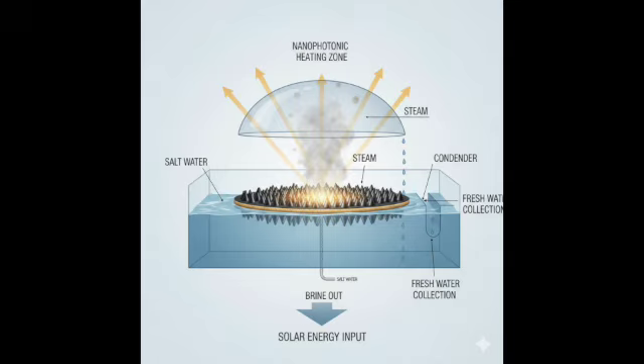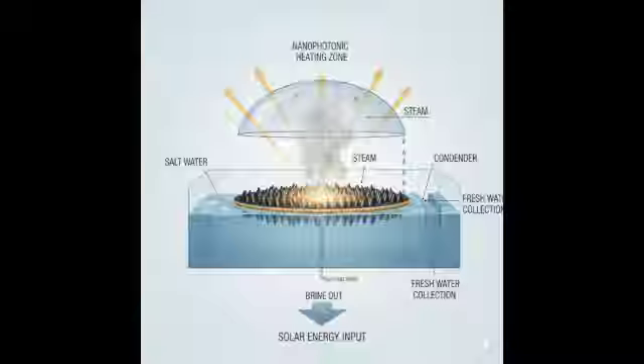Yes, it absorbs light well, but its real strength here is as an intermediate adhesive layer. You can coat a membrane with PDA and then easily attach other functional materials onto the PDA layer, things like carbon black nanoparticles for enhanced heating, or maybe a superhydrophobic molecule like FAS17 to improve wetting resistance. So it's a platform for building multifunctional surfaces. Exactly, and it's relatively simple, uses water-based chemistry, and PDA itself is biocompatible. A PDA-based coating achieved over 75% solar energy utilization efficiency in one study.